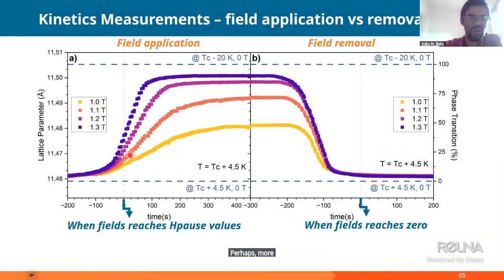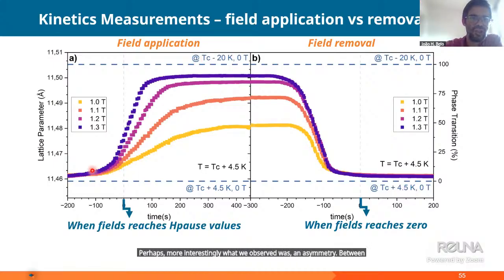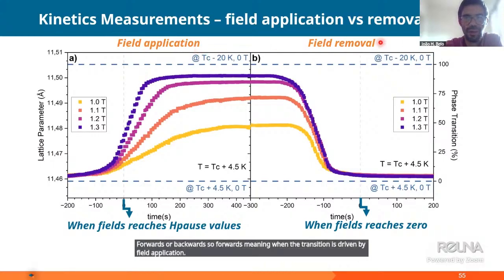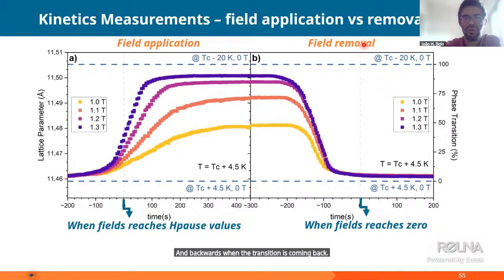Perhaps more interestingly, what we observed was an asymmetry between when the transition is forwards or backwards. Forwards meaning when the transition is driven by field application, and backwards when the transition is coming back, upon field removal. So you see here again the lattice parameter for 4 different H-pause values. We see the very long relaxations. And now we applied a similar protocol, which was basically just remove the field to 0 value and continue to track the lattice parameters. So we see that all these curves were shifted so that at t equals 0, all of them have already reached the field 0 condition. So there is no relaxation after the field has reached the 0 value. It's a very striking asymmetry between application and removal.